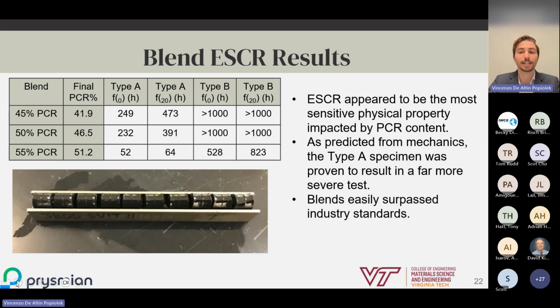Of note, we see that ESCR does appear to be the most sensitive physical property impacted by PCR content, seeing a significant decrease in performance after we surpass that 50% PCR threshold. This confirms to us that it is one of the more important properties to plan around and design for when creating these sustainable blends.